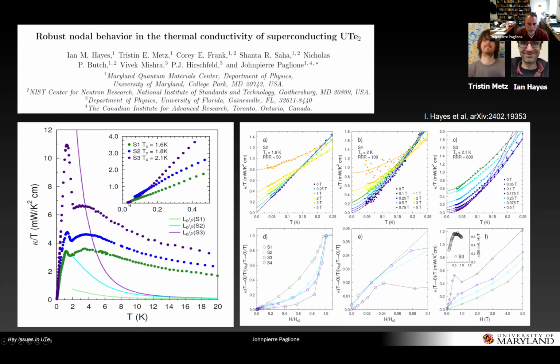And then the next question is, how does this evolve with magnetic field? That allows you to discern between different scenarios for the gap structure. So here's a comparison of 3 samples. You can see the TCs are different, 1.6, 1.8, and 2.1. Triple R's are different. And you can see that in all cases there is a very rapid rise in the residual term as a function of field.